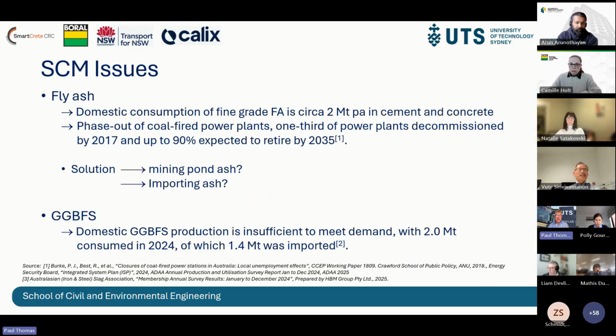That's really important. Camille mentioned, had a quick talk about the limiting supply of fly ash and GGBFS, and also possibly the quality as well. A lot of people are talking about mining pond ash as a possibility, or importing ash for fly ash. Problems there mean you've got variability in quality, but also by processing the materials you're starting to put embodied carbon back in. Similarly with blast furnace slag, in Australia we only manufacture about a third of our consumption - we import two-thirds of the blast furnace slag consumed in Australia, so it's already, to some extent, an issue.